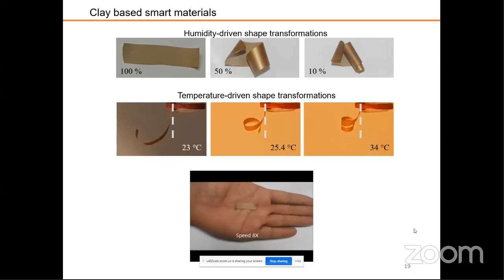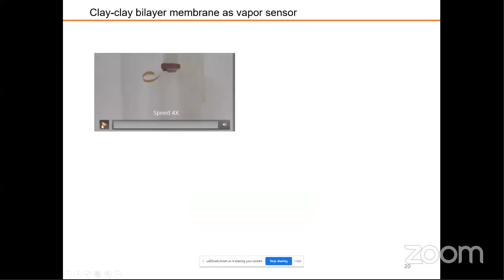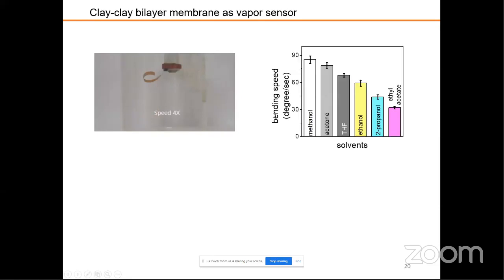Similarly, this material is also very sensitive to the surrounding atmosphere. If the atmosphere has some solvent vapor, for example here we exposed it to some methanol vapor, it immediately opened up. And the moment we take away the beaker with the methanol vapor, it goes back to its original shape. So it's very sensitive to solvent vapor, and it is very, very repeatable. Here we have shown that we have done this almost 50 times, and the speed at which it bends and opens up is the same. It's not changed much. Similarly, it's characteristic of the solvent we use.